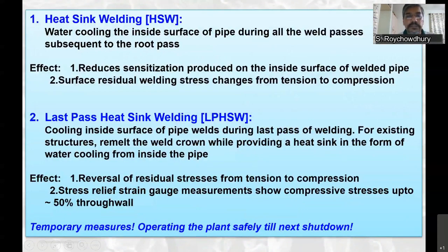Some stopgap measures you can take, like heat sink welding or last pass heat sink welding. It's mainly for, say, pipelines. When you're welding two SS pipelines, after the root pass, you pass cold water from the ID side when you are doing the subsequent passes to fill up that gap. What happens, because of the water, is the internal surfaces of the SS will not rise to temperatures reaching that 500 to 850, so that sensitization will be avoided.